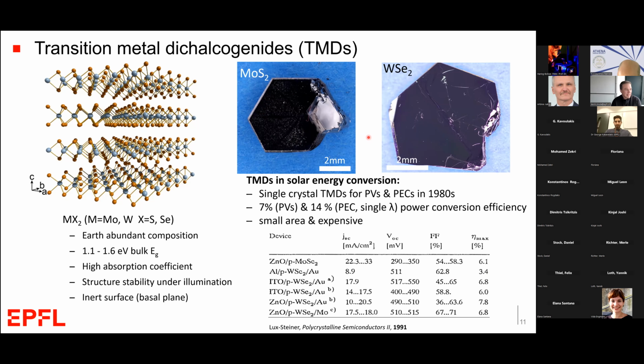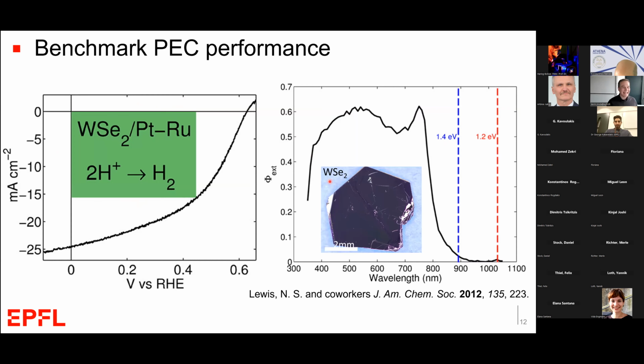Now, a little bit more recently, Nate Lewis's group at Caltech showed that a tungsten diselenide photocathode material performed exceptionally for the hydrogen evolution reaction. What they did was take a single crystal tungsten diselenide and put a catalyst on it, like this platinum ruthenium, and they showed short circuit photocurrent densities under one sun of almost 25 milliamps per centimeter squared. That's compared to the sort of 8 milliamps that we had with the CIS photoelectrodes that I showed before. So the performance is really, really good. The quantum efficiency is shown here. The high photocurrent is partly given to the relatively low band gap of this material of around 1.4 electron volts, but also to the high quantum efficiency of about 60% in this system. But again, the fact that this is a single crystal makes it difficult to imagine this over a large area.